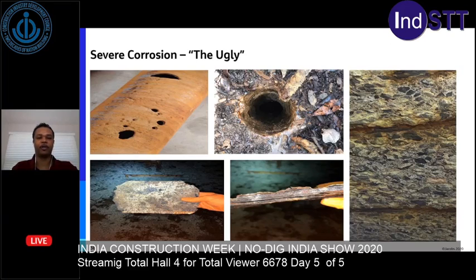So on this slide, you have severe corrosion. This is considered the ugly. At the top left, you can see some through wall corrosion on a pipeline. At the top center, you can see a well that used to be carbon steel, which is no longer there. On the right, you can see some rebar corrosion that has taken place from erosion corrosion. And also on the bottom, where there's a couple gloves in the photos, that used to be the roof of a carbon steel tank, which was found on the tank floor during the inspection. Next slide.